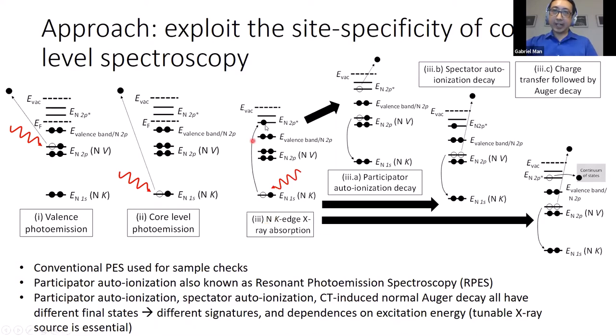By studying the decay of the core excited nitrogen 1s core level, we can say something about both the coupling in the occupied states between the organic and inorganic sublattices and the coupling in the unoccupied states. So this is one of the decay mechanisms. This is participator autoionization decay, where the core excited electron actually participates, and the final state is the same as valence photoemission, hence the name resonant photoemission. This is a local mechanism where the core excited electron has not left its host nitrogen atom yet.